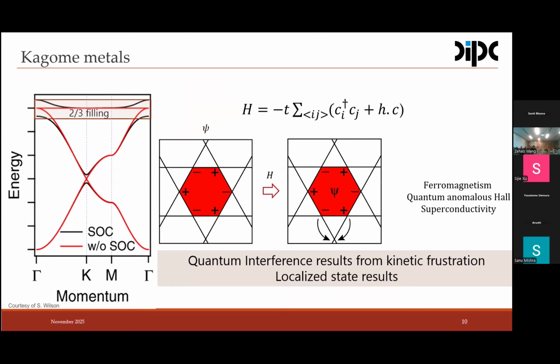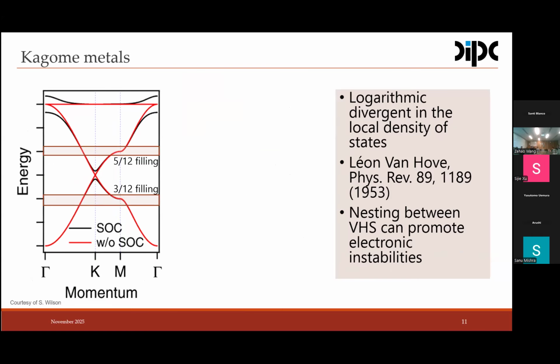So this flat band at the Fermi level can actually lead us to exotic magnetism or even superconductivity. There are predictions of high Tc superconductivity when the flat band falls at the Fermi level. In any case, what we are interested in